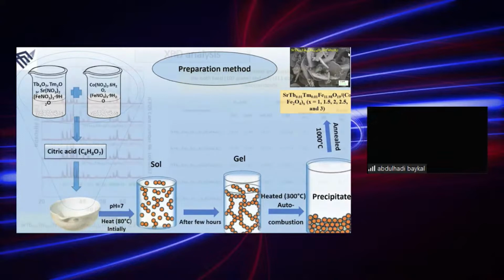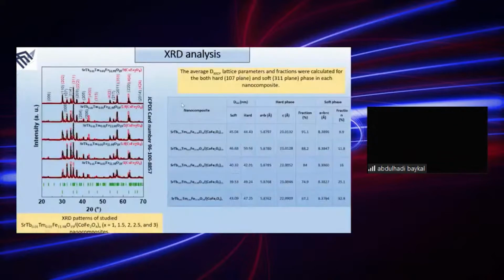And then this is the SEM image of one sample, which is true for X equal to 1. You see that it is very clearly seen that there are hexagonal plates in the morphology of the product. Now, if we continue, let's have a look at the characterization of our sample, our product. The characterization, of course, we did XRD. XRD is important for us to identify the composition of our products.